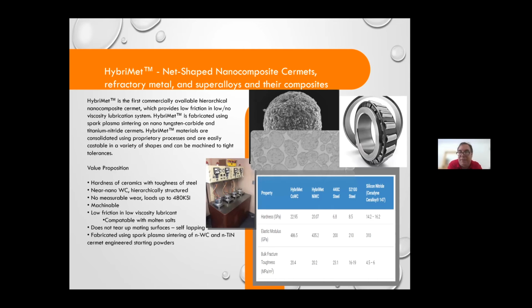Tungsten carbide is the baseline, but we also offer titanium nitride and borides. We put those into a matrix and get a structure that is both extremely hard and wear resistant, up to 2,600 Vickers, but also extremely ductile. So same properties as tool steel, 26 K1C, and significantly strained to failure. This has particular usefulness in high load bearing applications and wear applications, bearing sleeves.